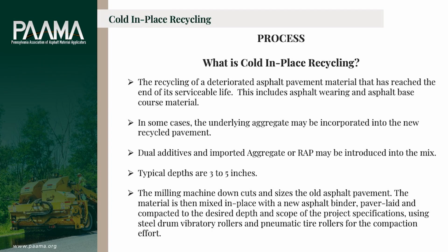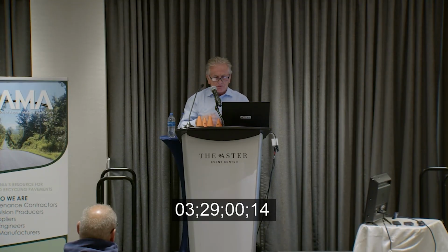And the milling machine down cuts. You can't take a regular milling machine, which is an upcut machine, and do cold in place. The reason being, if that's your pavement and an upcut machine comes under a corrugated or alligated section, it breaks it off in larger chunks and they segregate, they get into the mix and play havoc with the mixes. So a downcut machine is cutting downhill. As the machine moves forward, you're cutting down at the pavement and you're chipping it into a particle size. The faster the machine goes, the larger the particle size. So we have to judge whether we're going to do 22 feet a minute or 30 feet a minute, depending on the gradation we are creating behind. We try to make a 2-inch minus gradation.